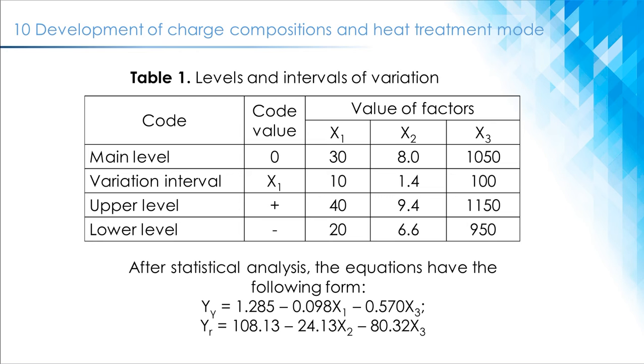The research objective is to obtain mathematical models expressing the aggregate's average density and strength on the leading technological factors. The mathematical planning method, followed by mathematical and statistical processing of the results, was used to reduce the number of experiments. A three-factor experiment at 2 levels is planned in work. The variables are x1, the content of ground shale as % of the total mass of dry components, x2, consumption of liquid glass as % of the total mass of the charge, and x3, firing temperature in degrees.